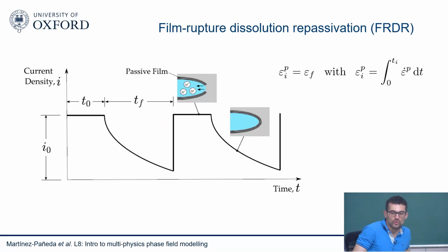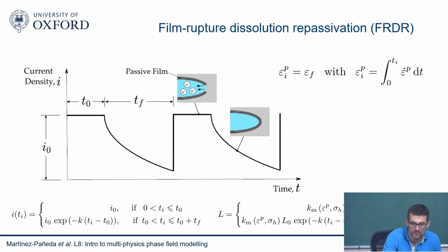So the idea is that you need to integrate. Every time you deposit a new film, you need to start measuring what strains you're applying. Straightforward, you are solving a mechanical problem, so you just accumulate strains. And then you also need to describe this process. There's always a little bit of time that it takes for the film to start forming, so you need to know that time. And then you need to understand how sharply the corrosion current density goes down for your given environment and material. That is typically characterized by an exponential function and by a parameter k.